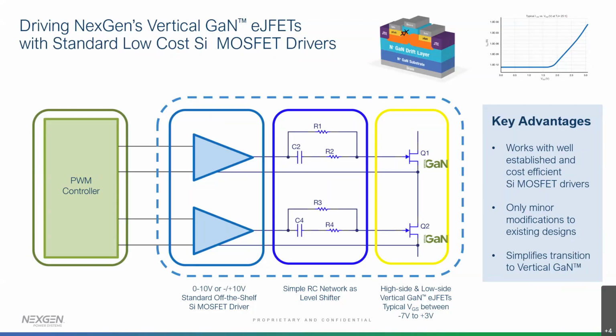We are basically carrying a small current through the gate-source diode of our device. When the silicon MOSFET driver delivers an on voltage, let's say 10 volts or so, then in a static case we control the gate-source voltage of our device through a voltage drop over the resistor R1, opening up the channel completely. But in a switching situation, you want to have a punch opening the channel quickly and driving the RDS(on) resistance down significantly, and this can be done by this RC network of C2 and R2, which basically gives the opening transition a punch.